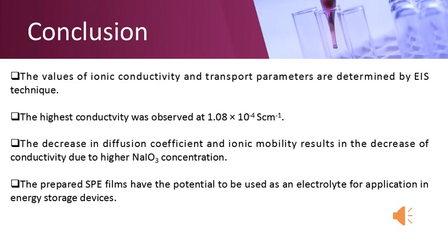The decrease in diffusion coefficient and ionic mobility results in the decrease of ionic conductivity due to the higher concentration of sodium iodate. It may also be concluded that the prepared solid polymer electrolyte films have potential to be used as an electrolyte for application in energy storage devices.